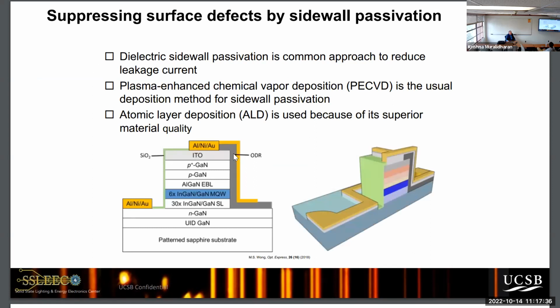So this is what the sidewall of our device looks like. So this is a semiconductor wafer, and you make a p-n junction. So here's the p-type material, here's the n-type material. So you need two electrodes. You need a top cathode, and you need an anode. So it looks like this. So one probe's here and one probe's here. And what happens is when I made this mesa, I created a huge number of defects. But what I just told you is if you use an ALD, you can have very high quality sidewall and passivate those defects. So we put it on each side.